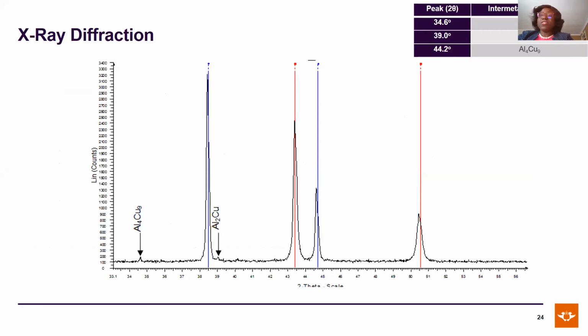This is X-ray diffraction of dissimilar aluminum and copper weld. If you look at the top right-hand corner, I have placed in there the various peaks at which these common intermetallic compounds will trigger in the welds. So we have 34.6, 39, and 44.2 for the various intermetallic compounds.